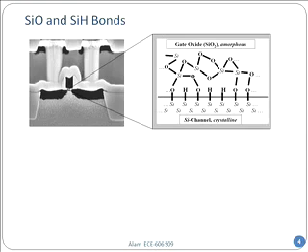Now the thing is that something that comes easy also goes easy. Something that you did in the last process step at a low temperature, this hydrogen stitching up the substrate with hydrogen bonds, as soon as you begin to operate the transistor, some of the hydrogen begins to leave with the electric field, and I'll explain why.